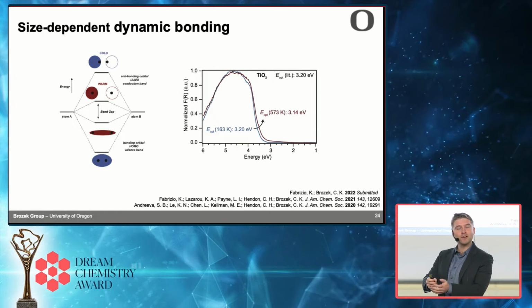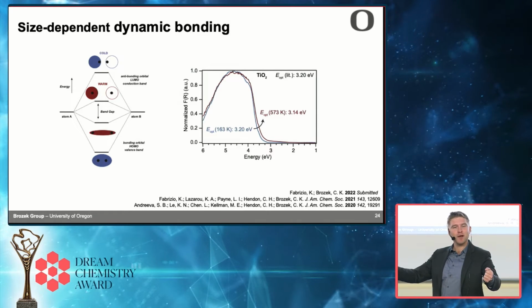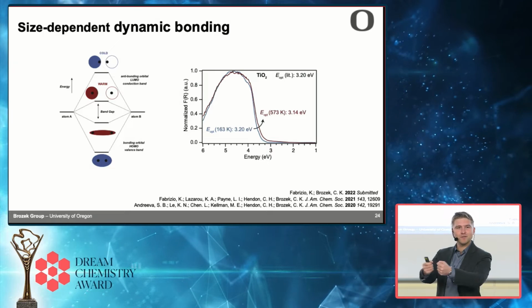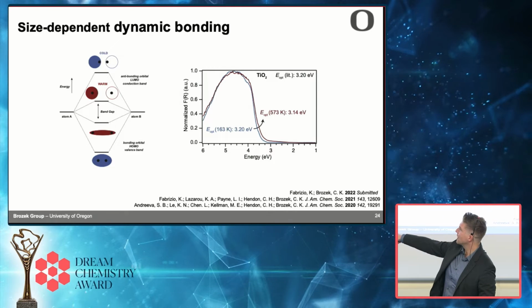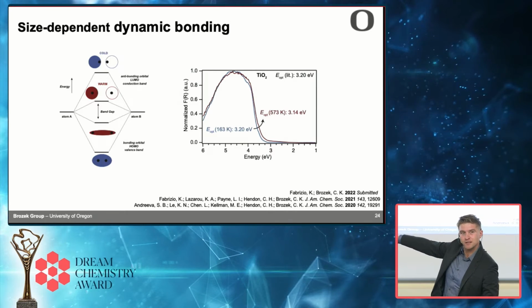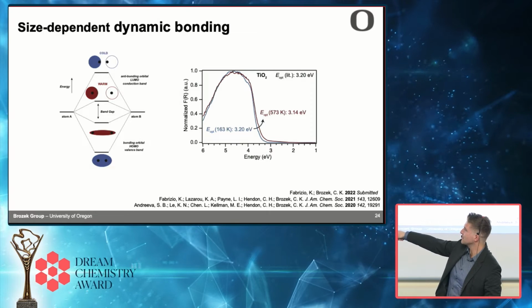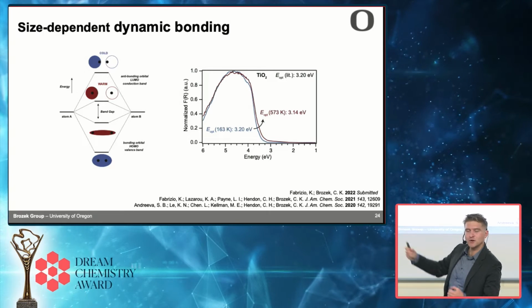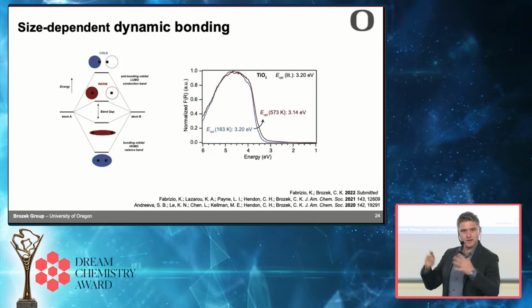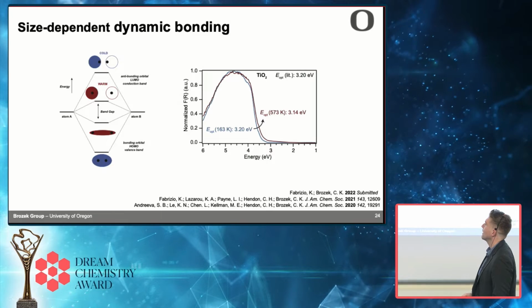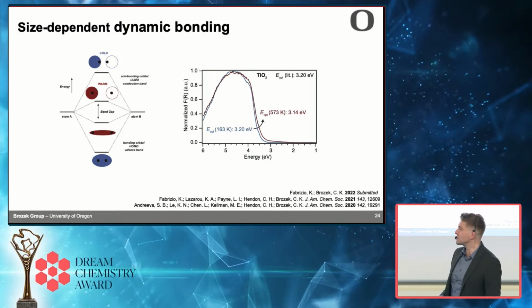You heat up the material, you get a lattice expansion, the atoms, the orbitals aren't overlapping as much, and so your bonding orbital isn't as stabilized, your anti-bonding orbital isn't as destabilized, and so your gap gets smaller, okay? So that's sort of the molecular explanation. What does this look like in a typical semiconductor?